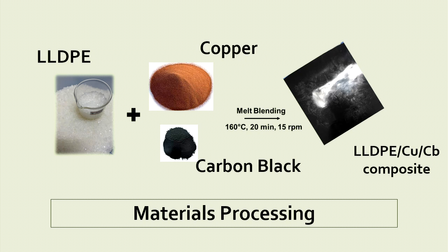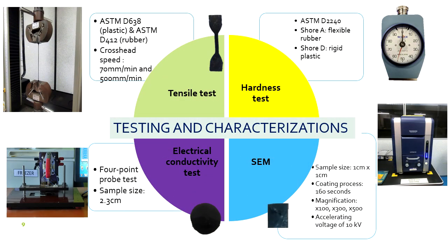This material can be processed through a melt blending technique whereby the copper and the carbon black will be blended with LLDPE at the temperature of 160 degrees Celsius for 20 minutes at 15 revolutions per minute. In order to test and evaluate our CPC's performance, several tests and characterization techniques were employed, such as tensile tests, hardness tests, electrical conductivity tests, and also scanning electron microscopy.